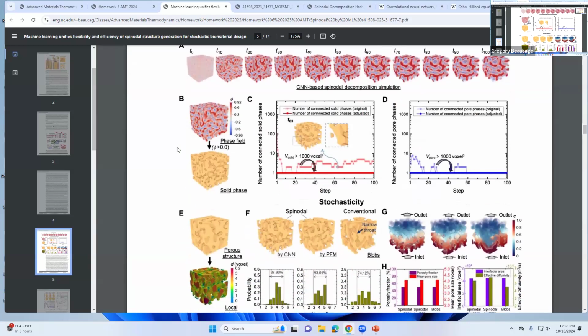All right, there's this other thing. He's only simulating a 64 by 64 block of this stuff. And maybe these things are microns, or maybe they're millimeters. A normal spinodal from metals, the size is going to be like a nanometer. The spinodal decomposition of metals, and of polymers, is going to be like 10 microns, because polymers are 1,000 times bigger than a metal, right? So basically, it scales with the size of the molecule it's separating.